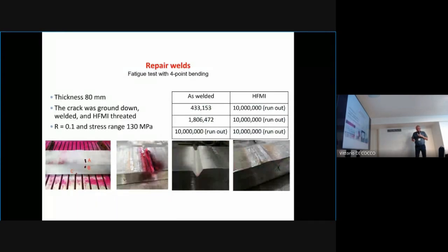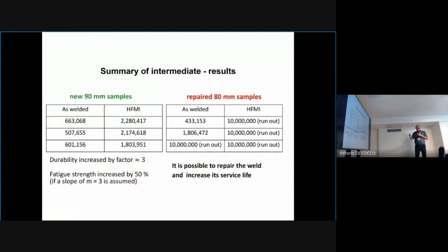You can see some pictures from the process. The crack was ground down, then welded, and HFMI was applied. And you can see again the results. With HFMI, no cracks, there are 10 million cycles. It means the technology works well on this type of weld. We can make the intermediate summary that it's possible to repair the weld and increase its service life. We can calculate that durability increased by a factor of 3 and fatigue strength increased by 50% when slope m=3 is assumed.